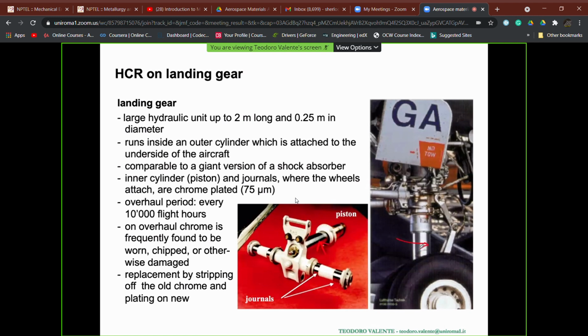They are applied by using solutions which have been identified. Obviously, there is, let me say in this way, some resistance from the industry side to move to this kind of solution, excluding the aircraft industries, because the process is more costly, I mean the HVOF, with respect to the simple electrochemical bath which can be used for classical standard hard chromium. But we do have indication at European level that the hard chromium replacement based on hexavalent chromium is to be completely avoided in order to put all the operators in a safe environment during the working procedure.